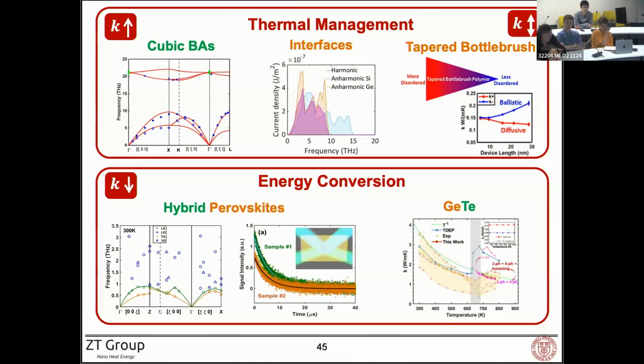So I was wondering, why not do supercells with different thickness to try to keep all the inelastic effects, both of the interface and of the bulk, and try to extract the interface resistance from those calculations at various thicknesses. So when you say supercell, are you thinking to put supercell in this framework or use a different approach? No, just using a standard approach with third order derivatives and periodic repetition of the interface. Okay, that's a great question.